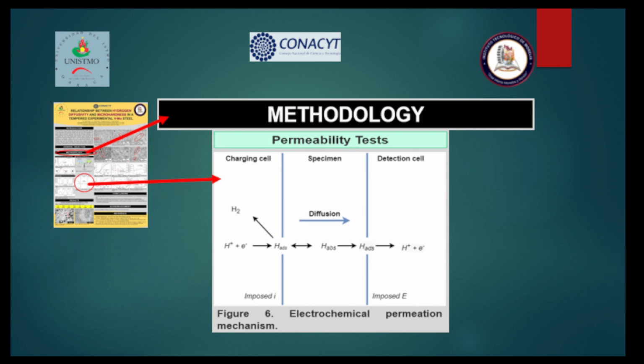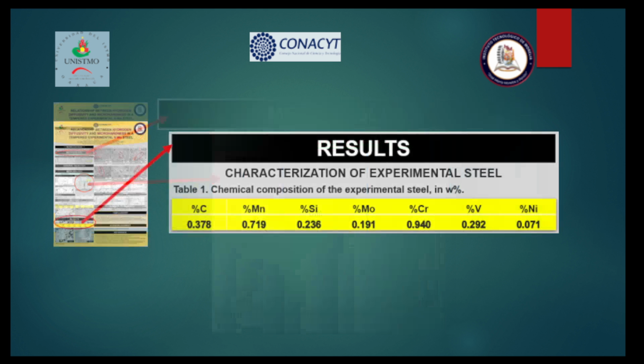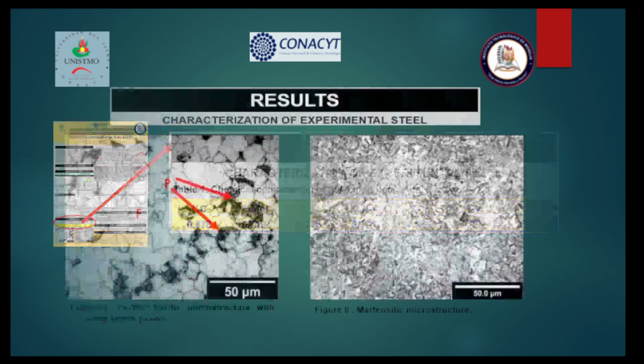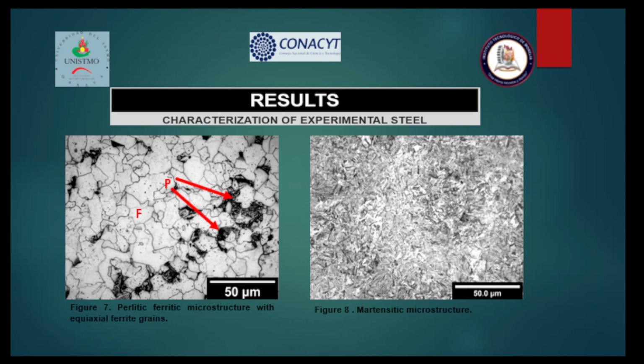Well, as a fourth point, the results obtained are presented. We have the chemical composition of the experimental steel, with approximately 0.38% carbon, 0.2 molybdenum, and 0.3 vanadium. We can observe the microstructure of the steel in the as-received condition and the martensitic microstructure that is obtained after quenching.